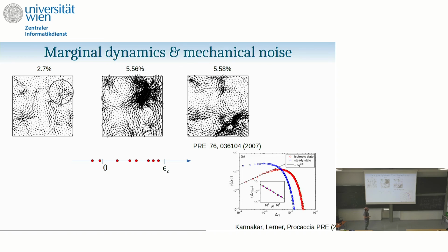This is by Lerner. I could find many others, people who started to look at the distribution of how close to threshold you are. What is the distribution of the distance to the next threshold? You take all sorts of configurations from steady state, and you measure the distribution of the elastic branches, of how far you are from the next threshold. And you see that you have a large tail. When you are in steady state flow, you create a large tail of zones which are near threshold, and this is really key to the fact that you have avalanche behavior. Yes?